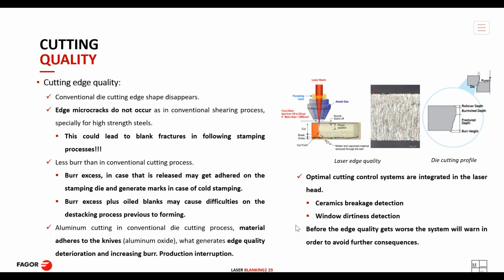So the edge quality is also an important matter. In this case, in the laser cutting, the conventional edge shape by mechanical cutting disappears, and this edge is more straight by laser cutting. And here, as you can see as well, this is a real photo from the microscope of a laser cut blank, and we can barely view any burr in this lower part.